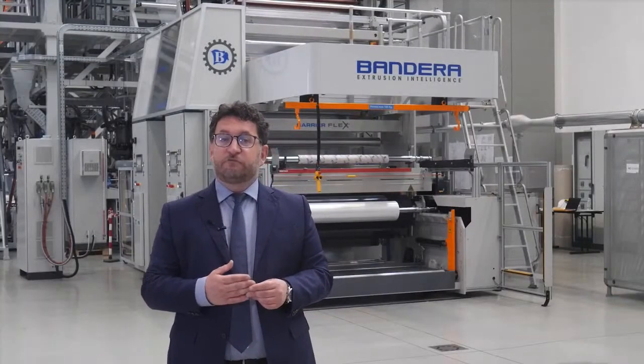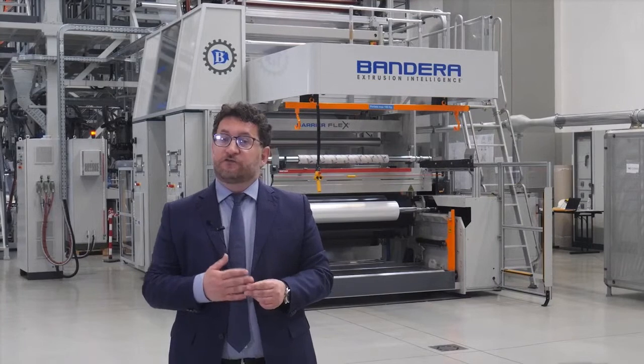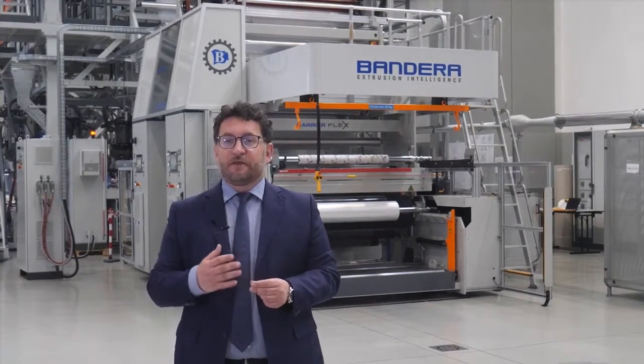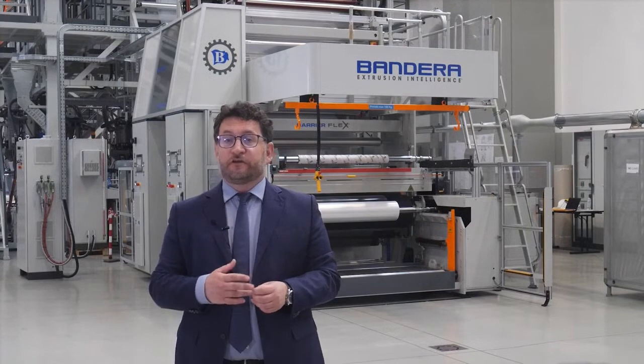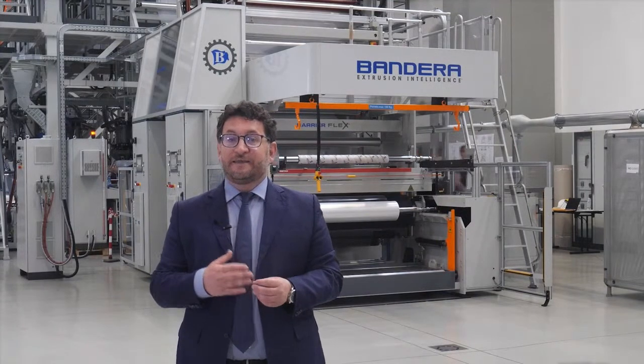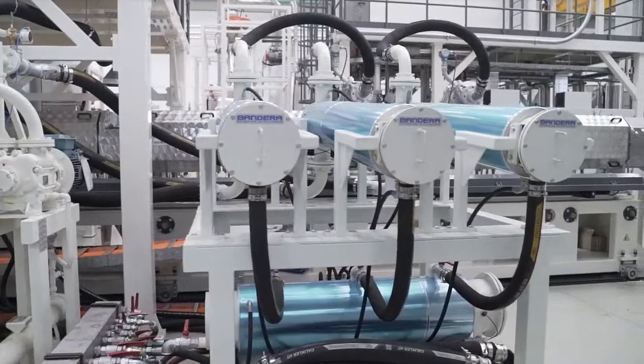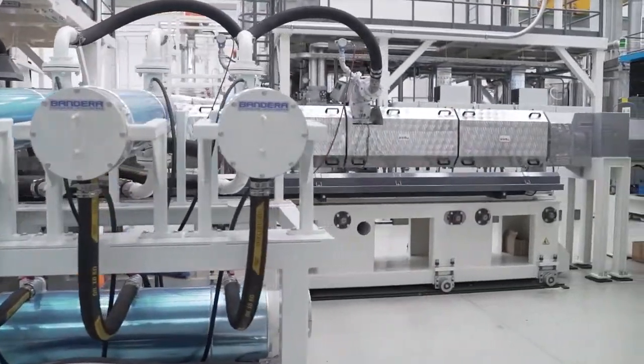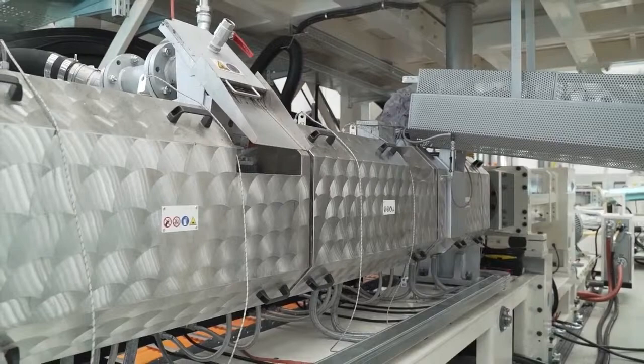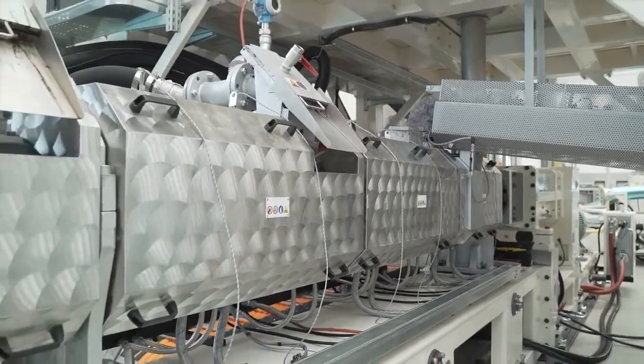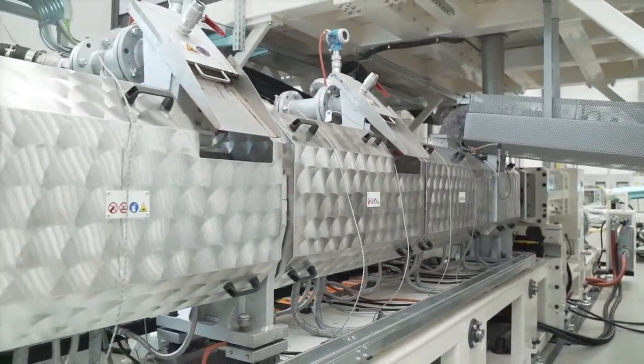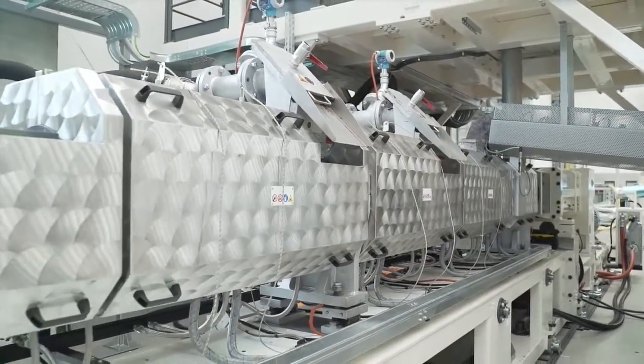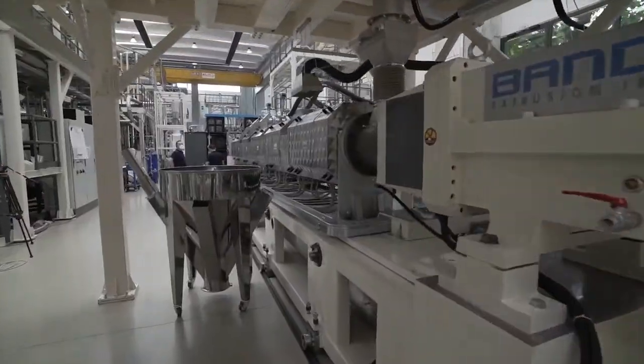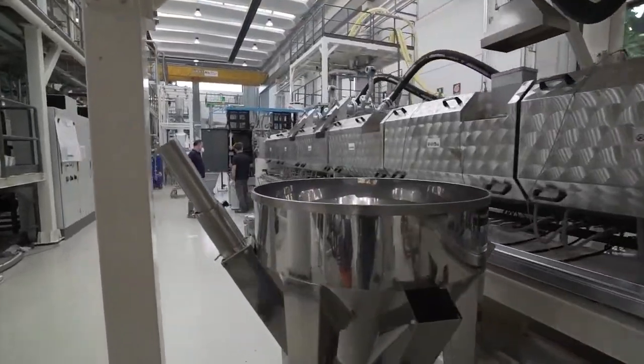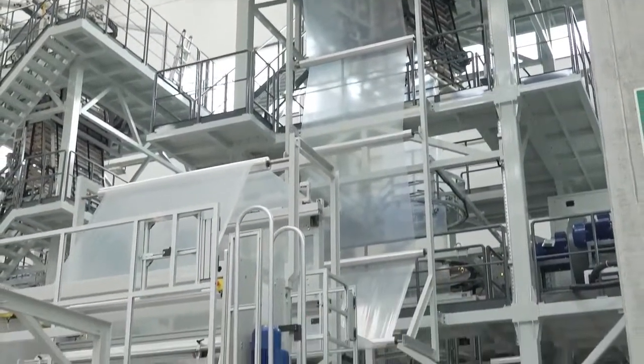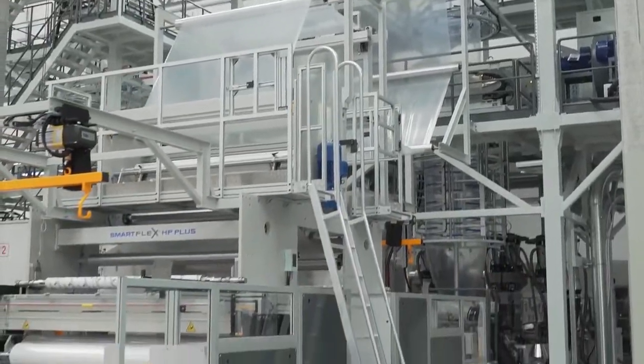We are indeed using the same twin-screw extruder, which gave us a lot of success processing post-consumer PET material for rigid application in more than 300 installations worldwide, getting now optimal results in a different application. Thanks to unique, specifically designed and patented features of the Bandera co-rotating twin-screw extruder, we can achieve a very low shear stress of the material, a very efficient triple degassing of the melt, a very precise oil thermoregulation of the extruder, and a very gentle and perfect mixing between polyamide or EVOH with polyethylene.